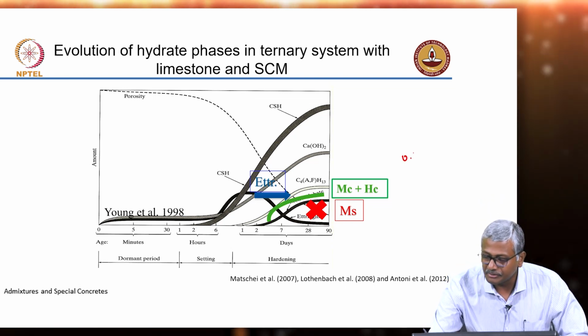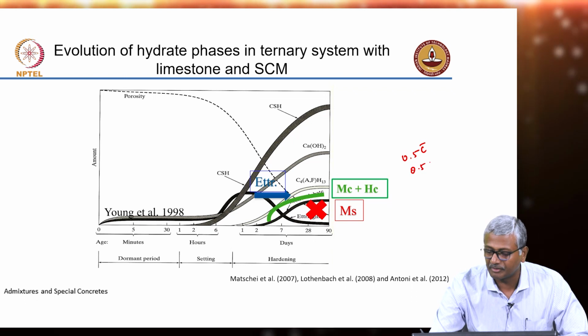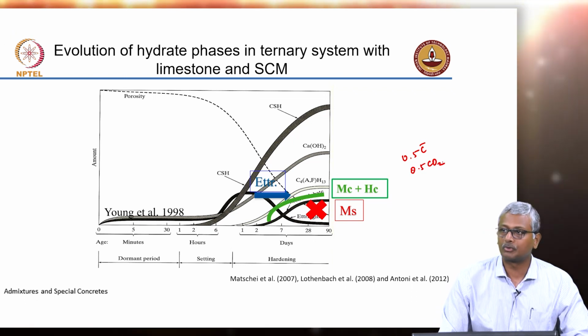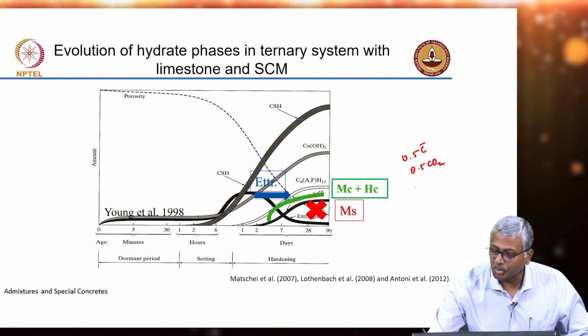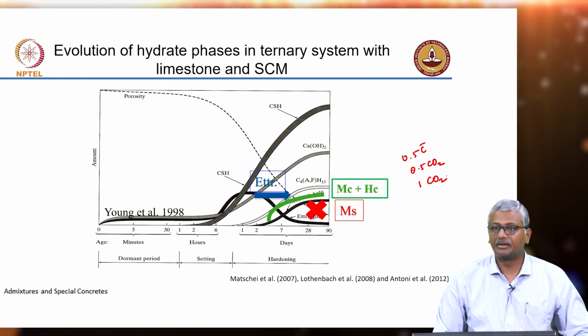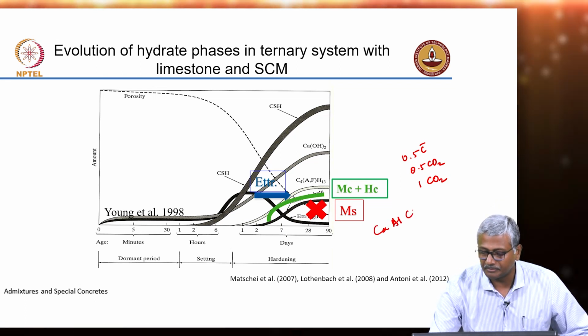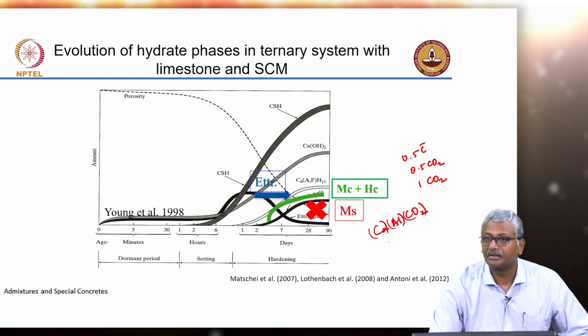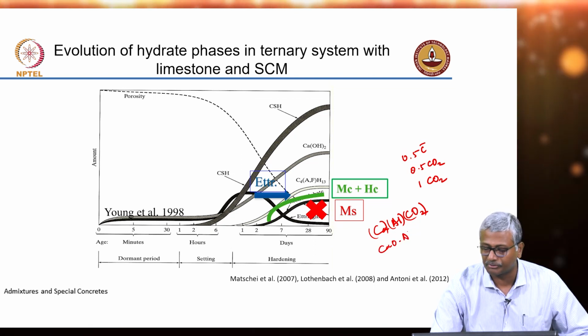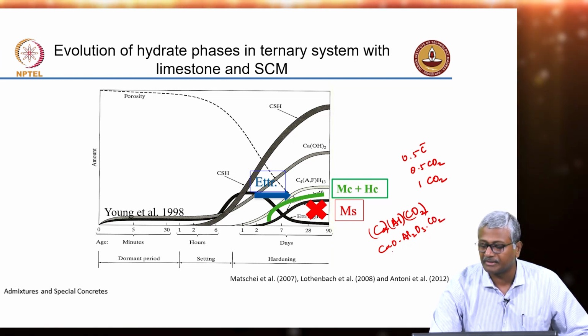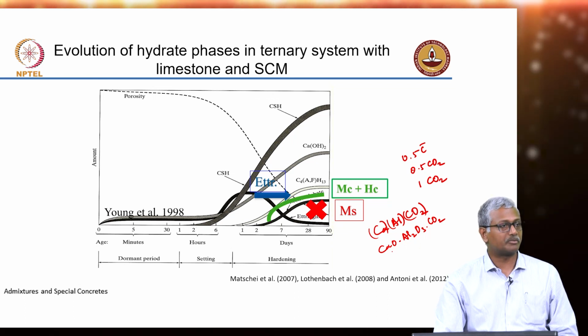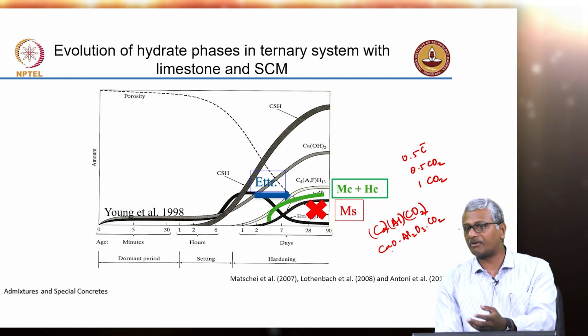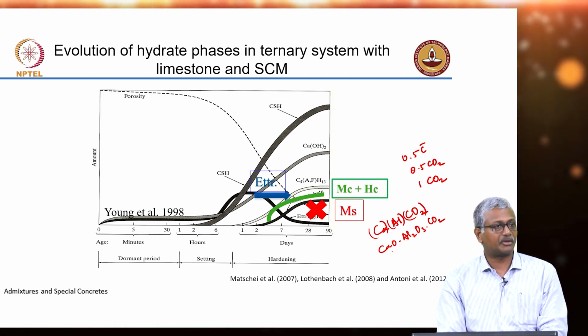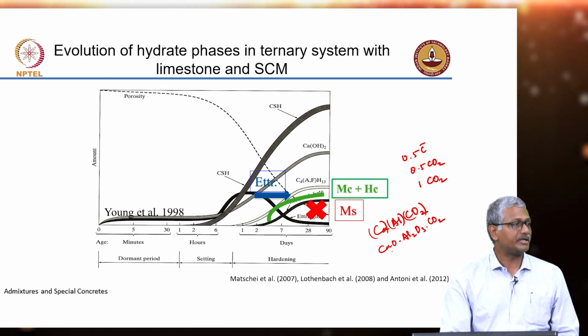So, hemicarbonate is 0.5 molecules of CO2 in the structure of the carbo aluminate. Monocarbonate is 1 CO2. Okay. So, basically it is calcium, aluminium, carbonate, or if you have to write it correctly in terms of cement chemistry, it will be a mixture of calcium oxide, aluminum oxide, and carbon dioxide. So, this is a monocarbonate system. Of course, I am not writing the stoichiometry correctly in terms of how much calcium, how much alumina, and so on, but when you have an aluminate source present like fly ash or slag or calcined clay, it will combine with the carbonate to start forming these carbo aluminate phases, right.